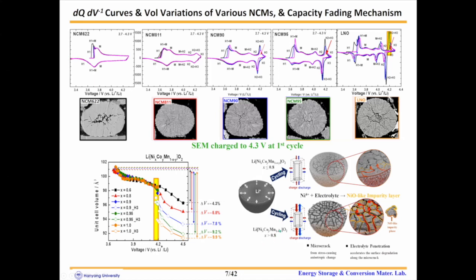This is the degradation mechanism of the NCM cathode. In the case of nickel contents more than 80%, the micro cracks formed from the H2, H3 phase transition propagated to the particle outer surface, facilitating electrolyte infiltration along the grain boundary into the particle interior, which accelerates surface degradation of the particles by reacting unstable tetravalent nickel with electrolyte to form a nickel oxide-like impurity layer, which leads to gradual capacity fading.